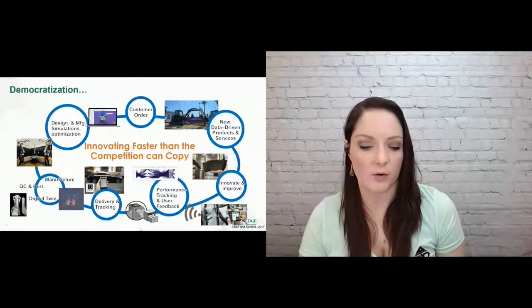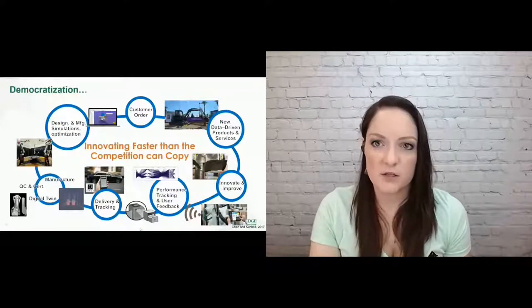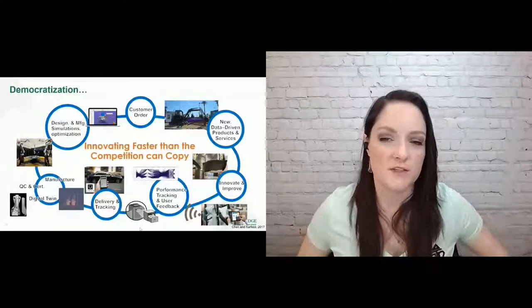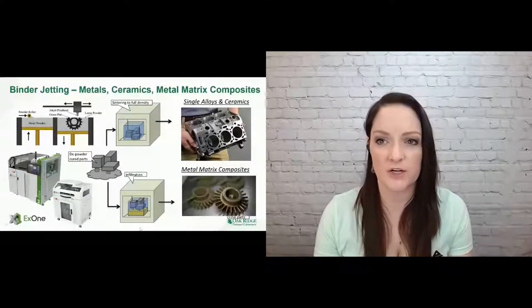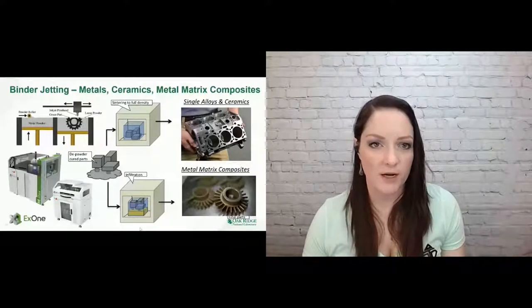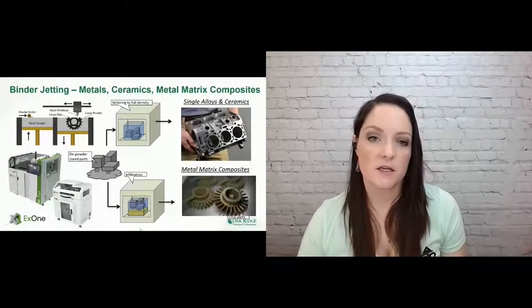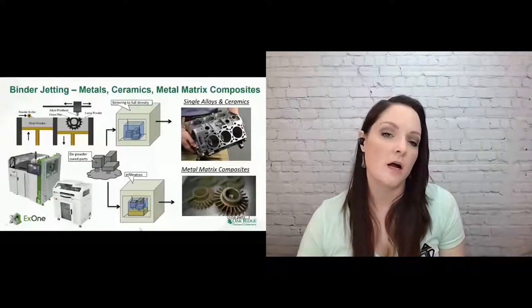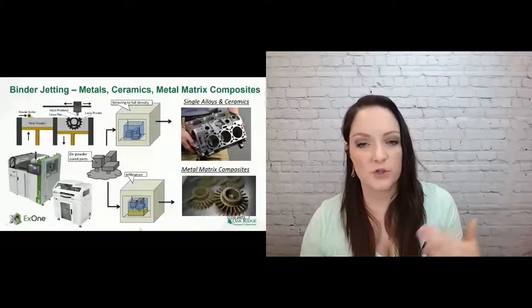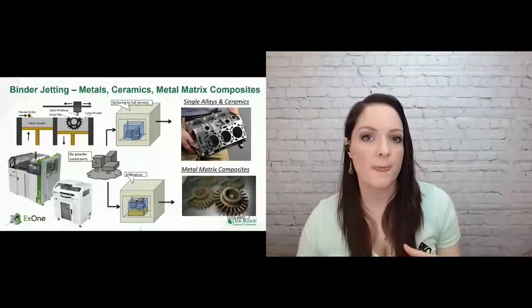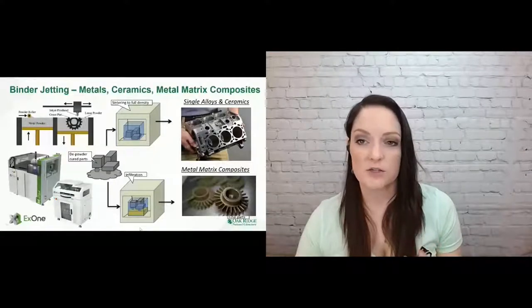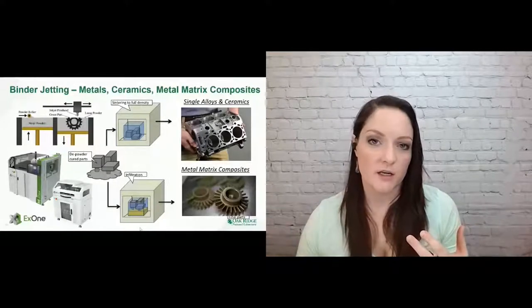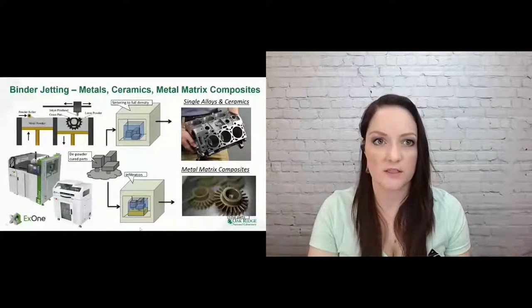So I think that's just a really cool vision for the future. And we at Oak Ridge are working on components of all of this. I just didn't have time to cover it. I did want to dive into my specific research. This is a women in 3D print conference, so we want to talk about what we're doing. So I work in binder jetting. We print metal powders with an inkjet print head. So we spread a layer of metal powder into a binder into that. And what we get is this preform kind of like a piece of pottery before it's fired. So to fire the part, we can, as I said before, infiltrate it with a metal that's at a lower melting temperature. So typically it will be bronze and steel or we can sinter it or fire it to full density. There's some shrinkage. There's some issues with that. But they have demonstrated that you can get fully dense single alloy parts more recently with this process.